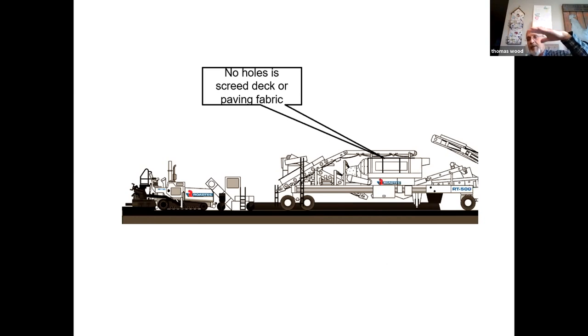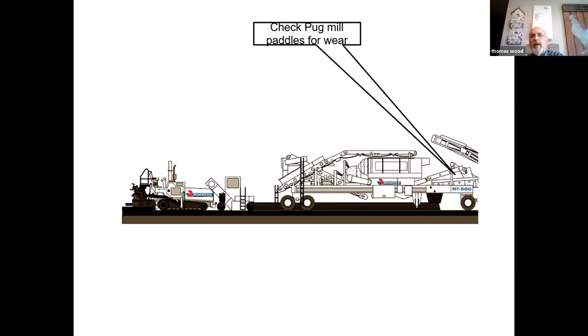If you get into paving fabrics, a lot of times they'll cover the deck up and the contractor will have to have people stand up there picking the fabric off the deck. Check pug mill paddles for wear on the emulsion when it gets hot. And they always complain about it getting sticky and too hard to work with. The contractor will say that in the pug mill. Usually it's because the paddles in the pug mill are wearing down.